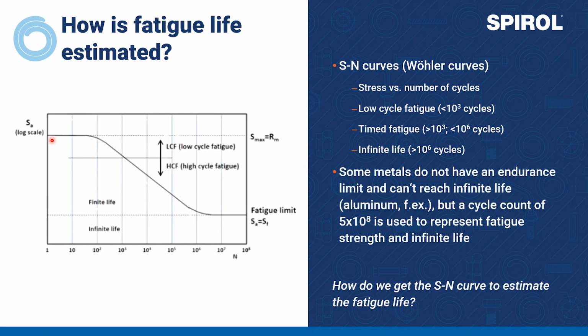And at that point, the stress or fatigue strength is actually very close to its static strength. And with more and more cycles, the strength under fatigue drops. This is the timed portion of the curve, where we see the life change a lot depending on the stress. However, once we reach 1 million or 10 million cycles or so, the drop in strength levels off, and we have reached what's called the endurance limit, where the life of the application is considered infinite.